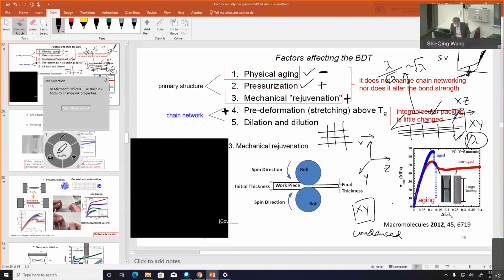So it turns out if you do it just uniaxially, you get a sample that's stronger when I draw this way and weaker when I draw it transversely. And that's true to the point that you can take a ductile polymer, subject it to melt stretching, and then examine it in the transverse direction, and your ductile polymer becomes brittle. Get it?